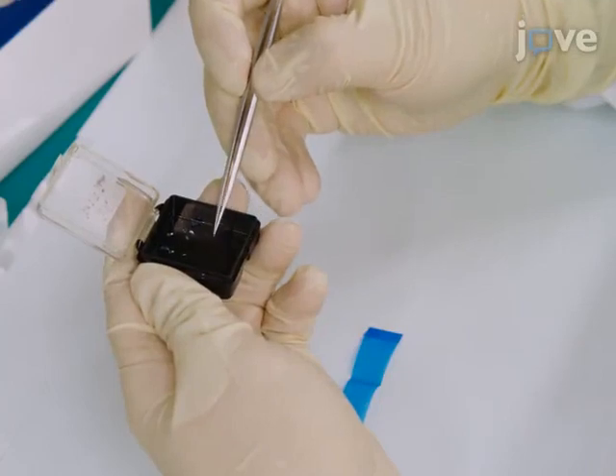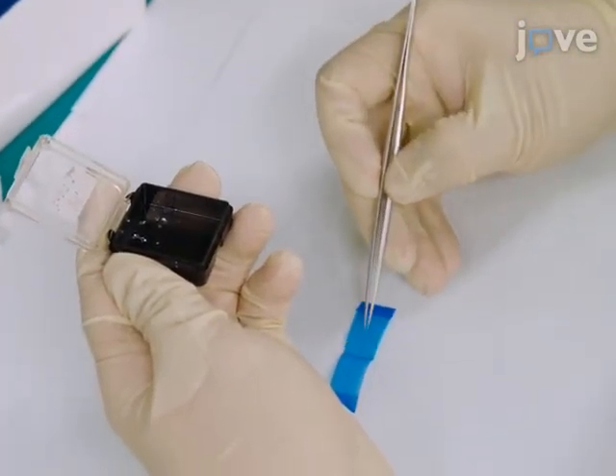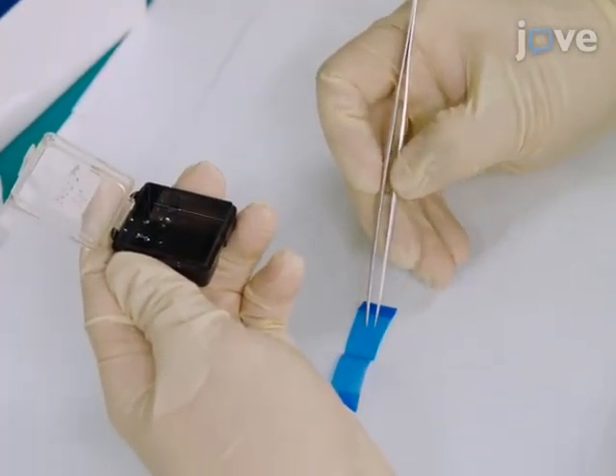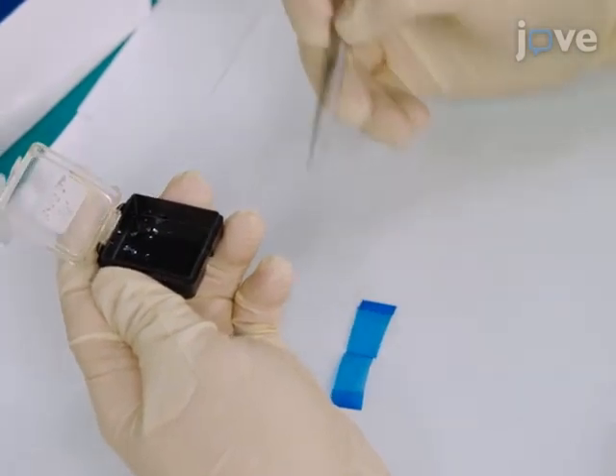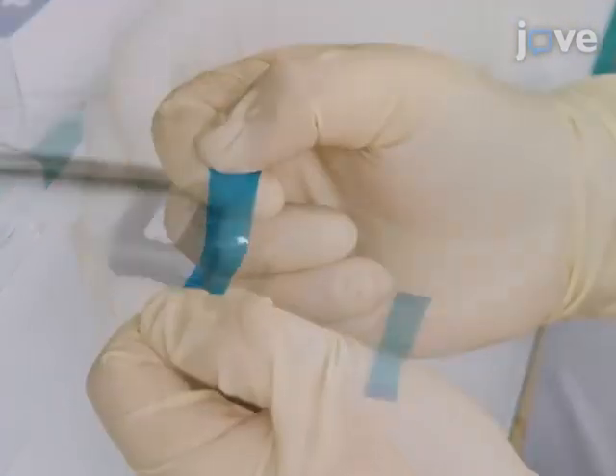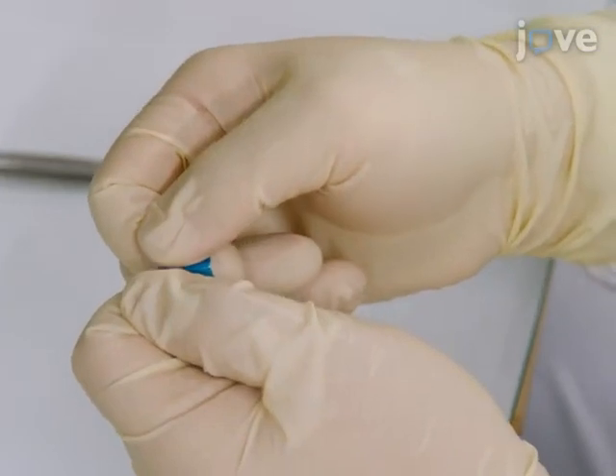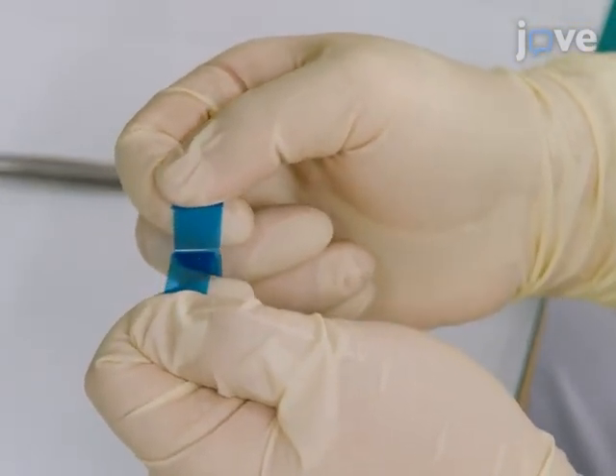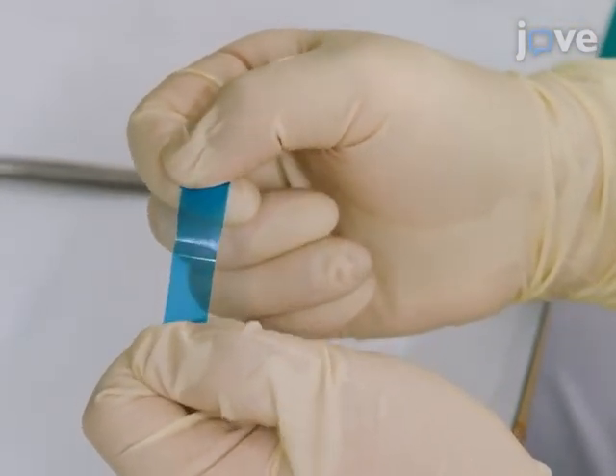To begin preparing the tungsten disulfide flakes, place a small bulk sample of tungsten disulfide on the adhesive side of silicone-free adhesive tape. Carefully fold and unfold the tape to mechanically exfoliate a thin layer of tungsten disulfide from the bulk. Continue folding and unfolding the tape.